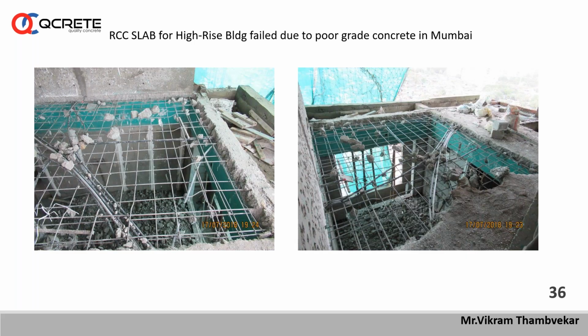See, here is another picture I'm showing you. The people used fresh concrete at site without checking anything, and of course that slab got sagged, and a number of cracks were observed. When we tested it, we found that the concrete was not proper. So we told the client to demolish this particular slab and recast it with good concrete. Of course, when recasting any RCC member, care shall be taken at joints because they are dry joints. So proper care shall be taken while putting the fresh concrete near the hardened concrete.